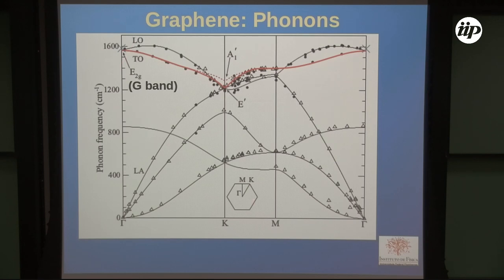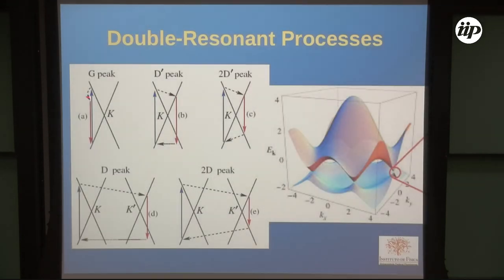And here, because graphene is not Td, it's D6h, like we learned this week, the symmetry is not so high. So we don't have triply degenerate phonons here. We have this doubly degenerate phonon and this non-degenerate one here. And Gustavo Cançado also told us that for symmetry reasons, this is only visible by infrared absorption, and this is only visible by Raman. So the G-band is a single process that comes exactly from these two degenerate phonons here. So we can understand it in this way.